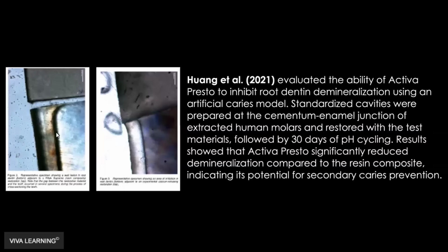And what he showed was that for the regular resin-based composites, this here is the root dentin, up here is a regular resin-based composite. This area where you could see a color change, that's not enamel and dentin. This part here is all root dentin, but the part where it's kind of yellowish in this different hue, that's demineralized root dentin. And what you can see is right next to the regular composite, there's an area, what we call a wall lesion, where there's more demineralization, like the demineralization is going deeper towards the pulp, deeper towards the right-hand side of the screen, next to the composite.